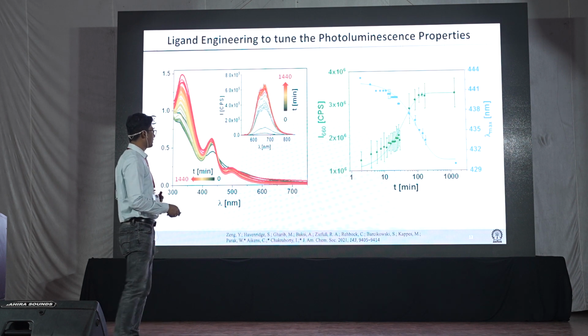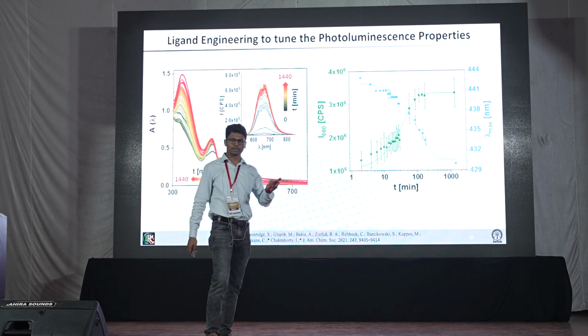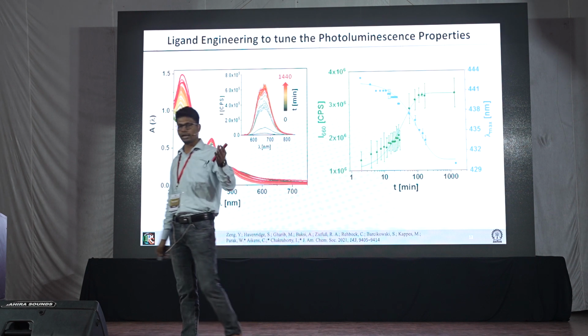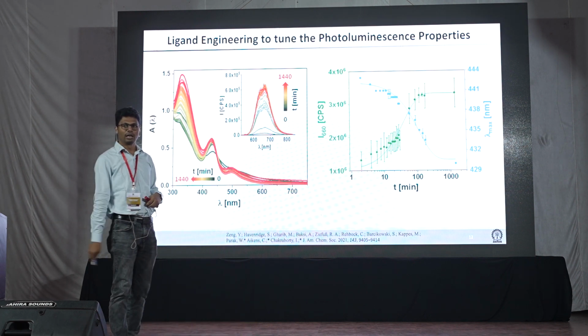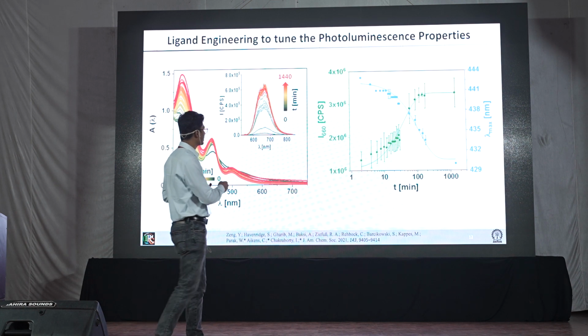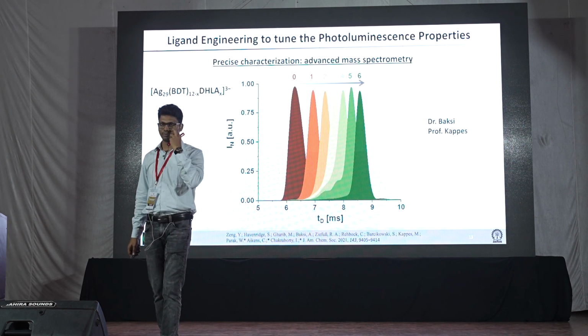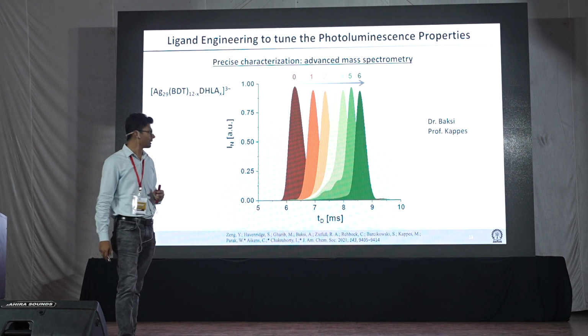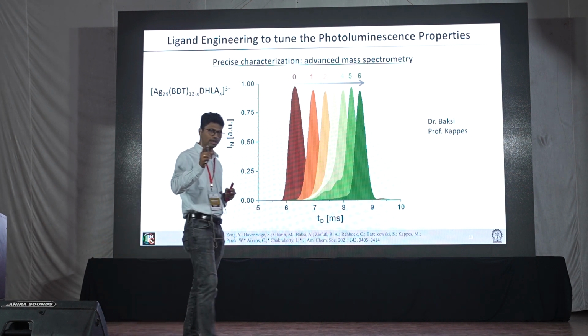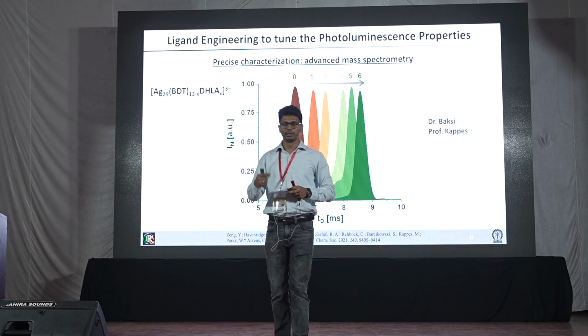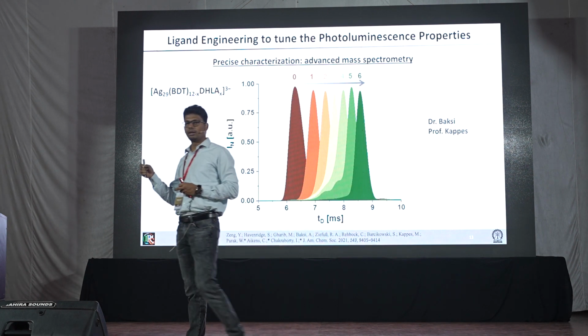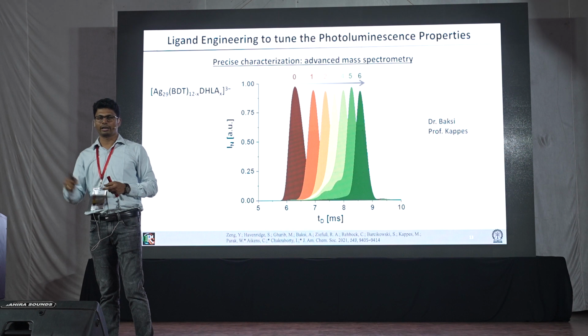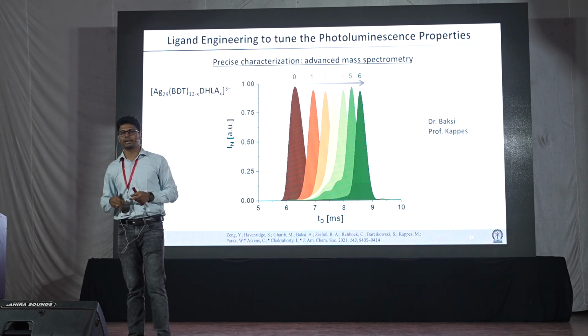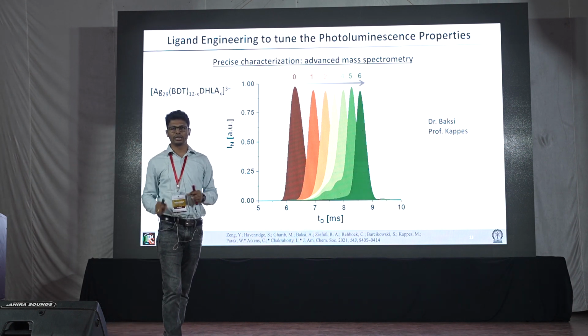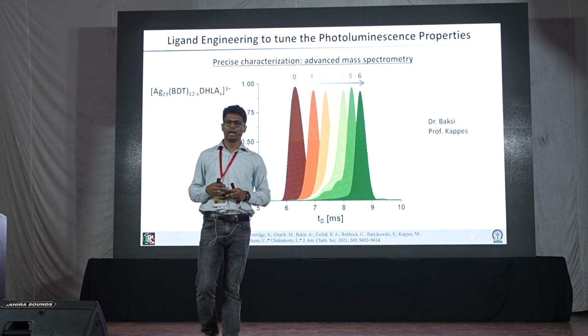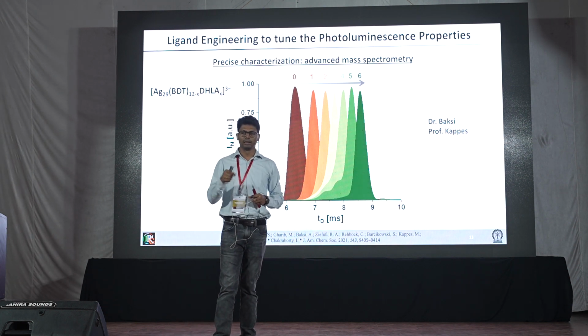So we went for a mass spectrometry-based analysis, where Ananya, who is one of my co-workers from my PhD time, was in Germany. She helped us in measuring the mass spec, and Professor Kappes' group from Germany helped us with the mass spec measurements, where we found that the DHLA, which is basically the dithiol, exchanged at a maximum of 6 ligands. That is what we found. So it's a confirmation that you have a ligand exchange. It is nothing unusual. It's a ligand exchange, and only 6 ligand exchanges were possible. That is what we came to know.